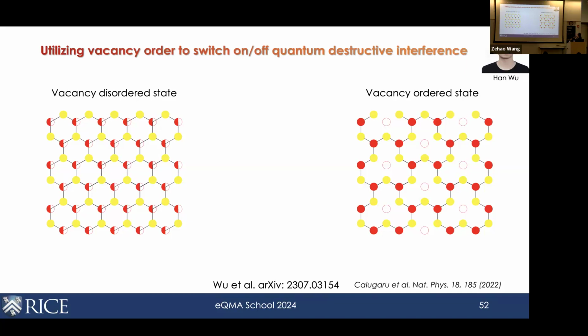And it turns out that in this system, which is the van der Waals ferromagnet, certain atomic sites have vacancies, and it turns out those vacancies can be ordered or disordered depending on how we thermally treat them. And the consequence is that if you look at the crystal structure, if you have vacancies that are completely disordered, on average it preserves a honeycomb lattice. But in another stable state, the vacancies can become ordered to give you an interesting lattice, which is a repeat of something that looks like this.